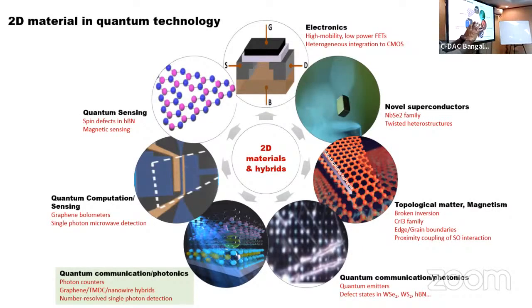The reason why? Because if you take silicon, even if you go to 10 nanometer technology or 5 nanometer technology, there is a very strong tunneling, and even in the off state there is a very large amount of current. This is called drain-induced barrier lowering in electronic devices. Now that is inversely proportional to some power of the thickness of the channel that you have created. Now imagine a two-dimensional material like molybdenum disulfide, which is just about 0.3, 0.4 nanometer thick. All this miniaturization becomes significantly easier, and the drain-induced barrier lowering problems are much lower. So we actually can create electronic devices which are far smaller in size and lower in energy consumption.